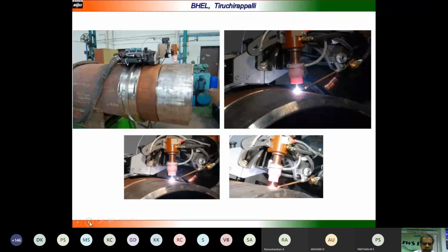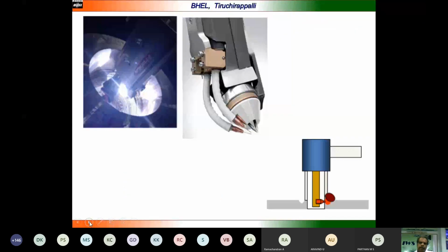The other advances are that TIG cladding is now taking place, and the twin torch tandem TIG welding. Two electrodes and two filler wires can be added in the material, and that can be used for deposition of weld metal, and even 3D printing. They are using the process now. It can be used for surfacing or cladding as well as for welding.